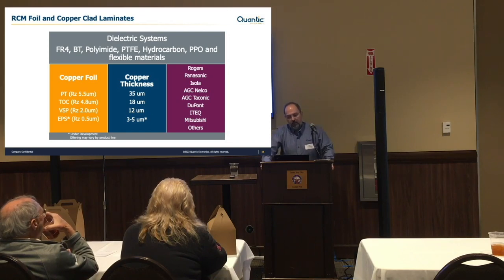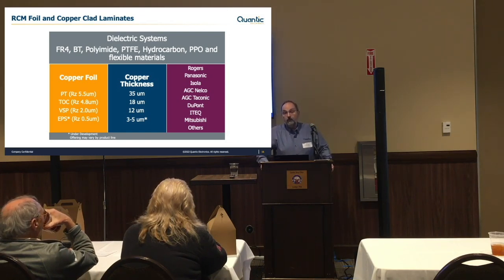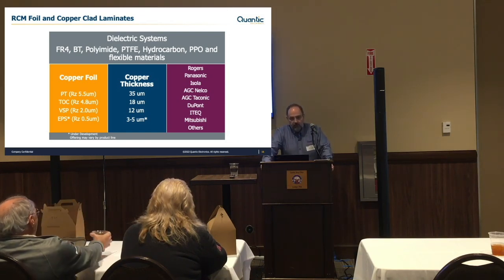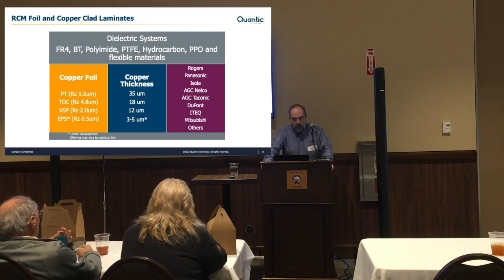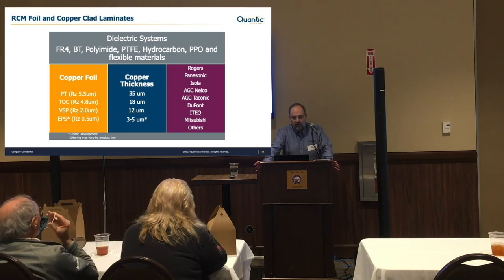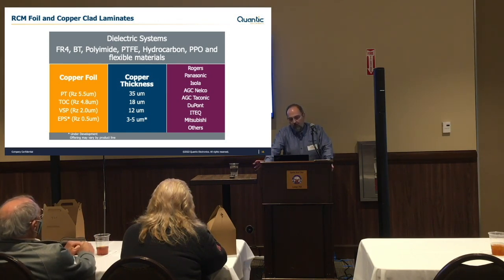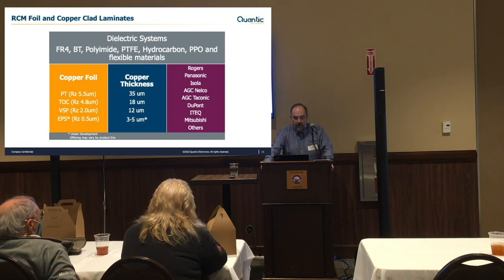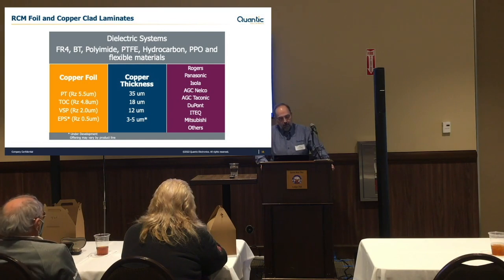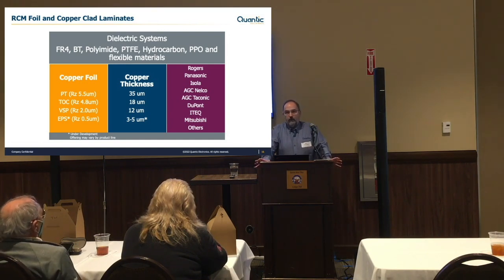And what's nice is that we've worked with the laminate suppliers, so we basically can take the standard copper foils, and we have different profiles. We could use everything from a relatively rough profile down to some very smooth copper profiles, depending on the need. And the basic copper thicknesses go from 35 micron, 1 ounce, half ounce, 12 micron, and now we are working on a developmental project where there's a 3 to 5 micron copper on a carrier.